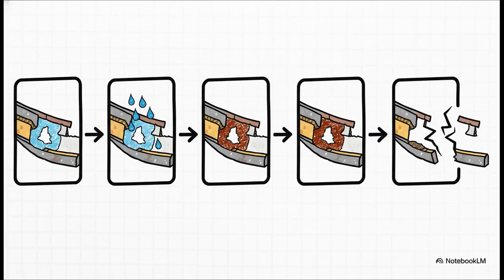So this was the deadly chain of events. It all kicked off with a tiny manufacturing defect, a little gap or a void in the glue that was holding a weight inside the blade. Somehow, moisture got into that gap and started causing corrosion. That corrosion then started a fatigue crack, and that crack just grew silently, getting bigger with every flight until the blade just couldn't take the stress anymore, and it completely failed.